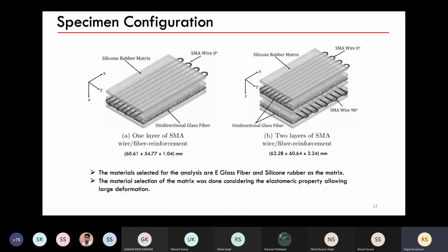So for this, we had two different structures in the beginning. For the first one, it only gave us a unimorph behavior, so the bending was only in one direction. We had our shape memory wires aligned in the 0-degree direction, which is the x-axis, along the longitudinal direction. As we heat the wires, they are going to shrink. Because they are at an offset, the below part of the structure is not going to shrink, so it is kind of putting the wires in a constrained form. Because the wires are still shrinking from the heat, the entire structure is going to bend along this direction.